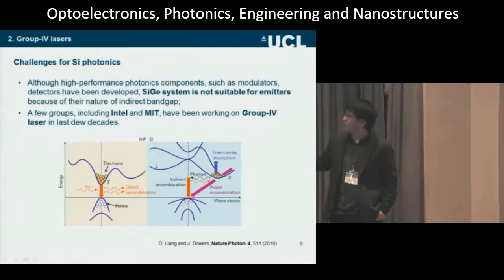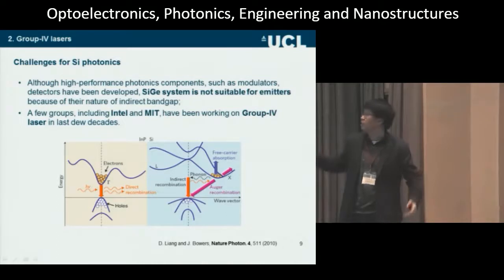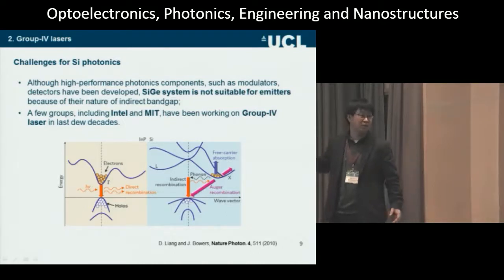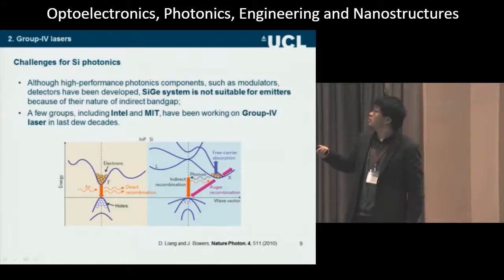For this one, you can easily get a lifetime of at least 1 to 2 nanoseconds. But for this one, you get a millisecond. That's a 10 to the 6 magnitude difference. Even like that, in the last 30, 40 years, a lot of big groups still work on silicon laser, pure group 4 laser, like Intel and MIT.